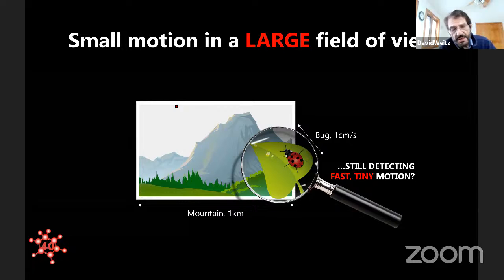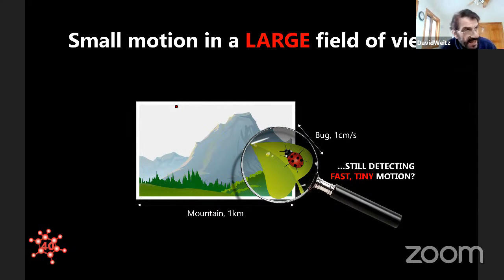Okay, so Stefano also said, well, this is all very good, but as you make the sample more and more stiff, then the amount of motion you get becomes harder and harder to see. And he asked a question, could he figure out how to measure a very, very small motion with a very large field of view? Already you're doing pretty well, because what you do is you image the speckles, because before what you were seeing was just like a little point, a little speckle. You can measure the displacement of a speckle. So you can measure sort of micron type displacements. But he asked, can you do even better?